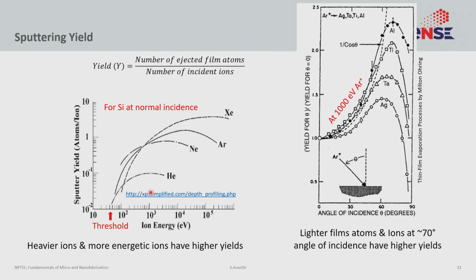Okay. Now, as you can imagine, that sputtering yield will change with which inert gas you use. So theoretically, you could use helium, neon, argon, or xenon. But if you were to use helium, you would actually not get a very high sputtering yield, and that is simply because helium is a light atom. So it will take a lot more energy or several helium atoms to actually eject one metal particle out from a metallic target, which is much heavier. As you go from helium to neon, the sputtering yield increases, argon increases further, xenon increases even more. However, xenon tends to be very expensive and for practical reasons is not used. Theoretically, you can use it.